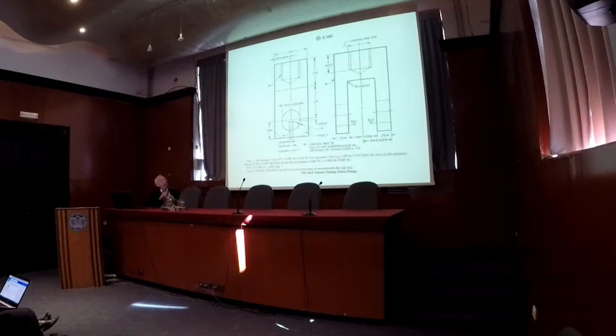Here's a clevis that you would use for compact specimen. You might notice here, specimen goes in here and then a pinhole goes through that. In the standard, it says that the pinhole should not be exactly round, but should have a flat portion, and you want the flat portion so that when the pin is sitting there, it doesn't hit against the sides.